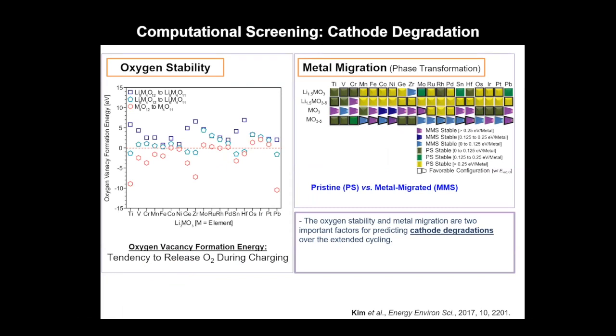And then the final screening criteria, which you might apply to a problem like this, would be something to do with cathode degradation. So for example, on the left here, we looked at stability of these materials with respect to oxygen release. We looked at the oxygen vacancy formation energy of these materials as a function of the lithium content in the materials. We're able to screen out materials that look like they're very unstable with respect to oxygen loss. We can also look at things like metal migration in these materials that would lead to undesirable phase transformations as a function of charge and discharge and so forth.